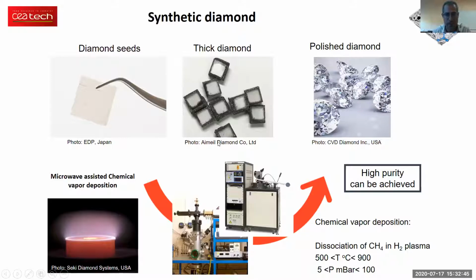Synthetic diamond is basically the same diamond as we find in nature. This is the crystalline form of carbon, sp3 hybridized carbon. The only difference is that this diamond is grown in the lab, using these big machines. It only grows on diamonds, so we need to start with a diamond seed. This is an example of a single crystal diamond plate. We put it in the reactor in a hydrogen plasma in the presence of methane. Methane is a source of carbon to grow our diamond, and after a few hours of growth, this is what we get, a thick diamond film.